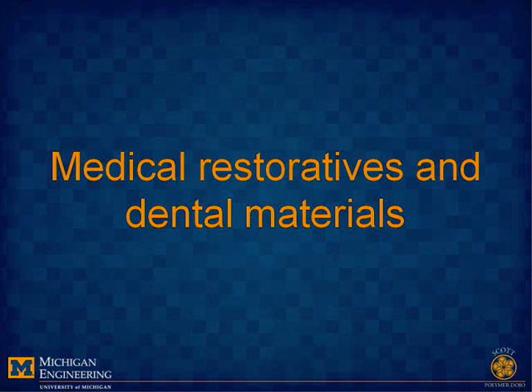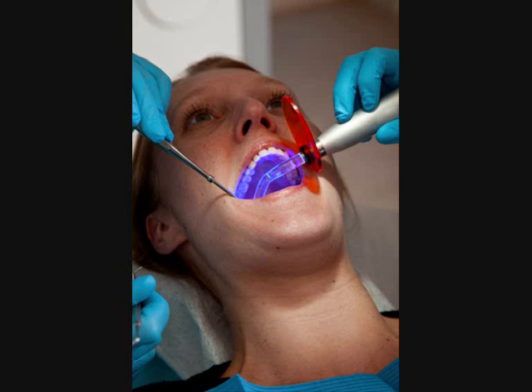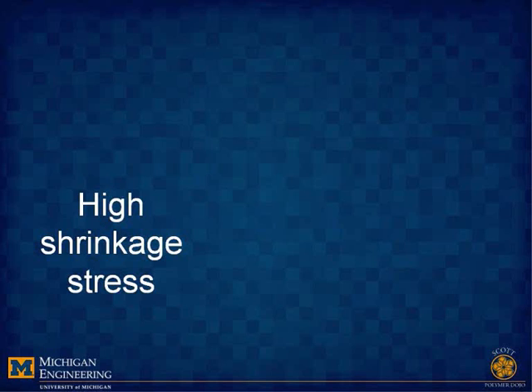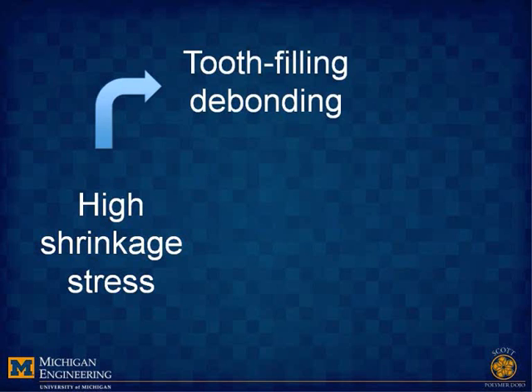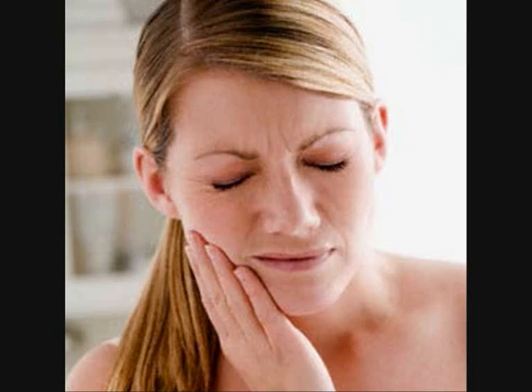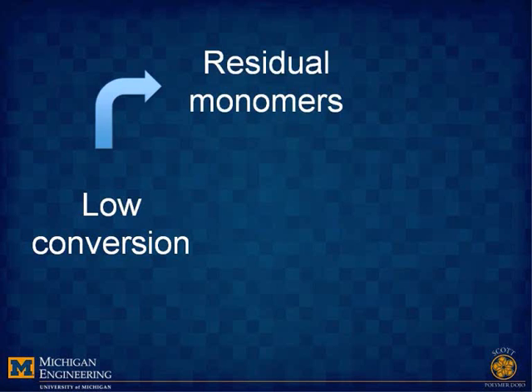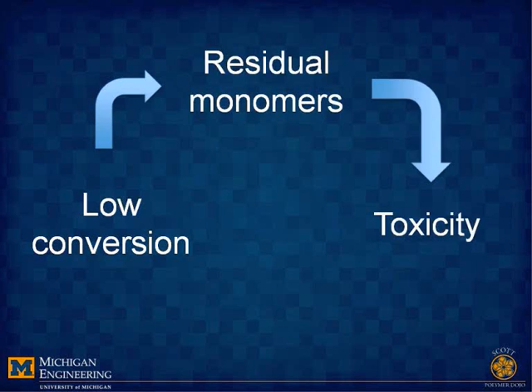An extended goal of this project is to develop UV-curable dental resins using these thiol-ene formulations. The well-known class of methacrylate resins show high shrinkage stress that leads to debonding of the resin from the tooth enamel, causing secondary caries. Also, lower conversion results in unreacted monomers leaching into the oral pathway, proving to be toxic.